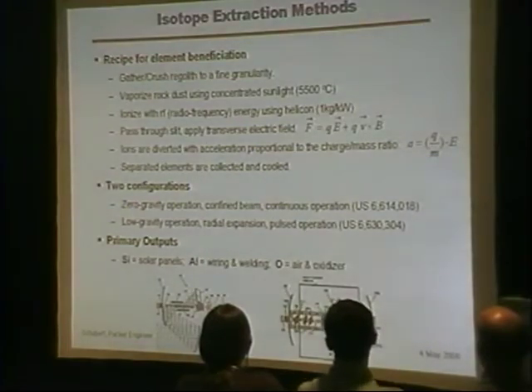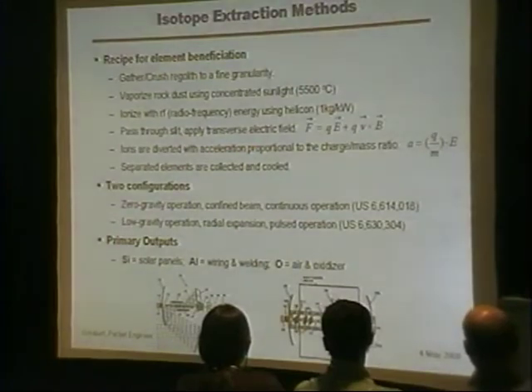transverse electric field. Isn't regolith already very, very fine, or do you need even finer? No? It's a range of sizes, including big rocks. So if we apply a transverse electric field by the Lorentz force law, we get a force on particles by their charge to mass ratio. So we basically make a rainbow of elements and can collect those at different locations to get the different elements. So we can get these separate elements.